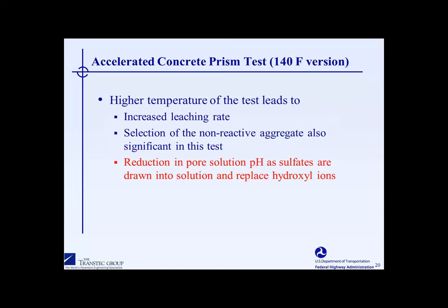The last point that I'll talk about here, and I'll highlight it in the next couple of slides very quickly, is that not only are we causing more leaching, we also dry the concrete. The prisms themselves actually tend to dry out more during the course of the test. But in addition, the pore solution in the concrete is also affected by higher temperature exposure. When we increase the temperature to 140 degrees Fahrenheit, we actually start to dissolve ettringite, which is a crystal inside concrete. The sulfate that gets released goes into the pore solution, and the net effect is that the pH actually drops inside the pore solution.